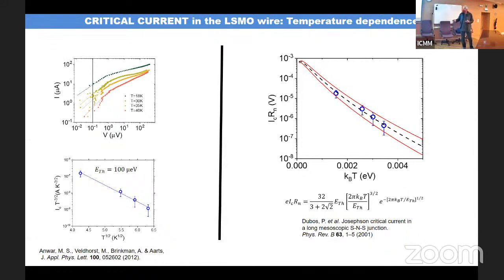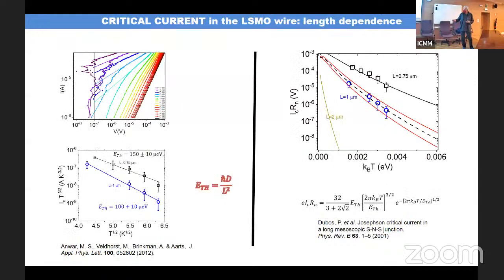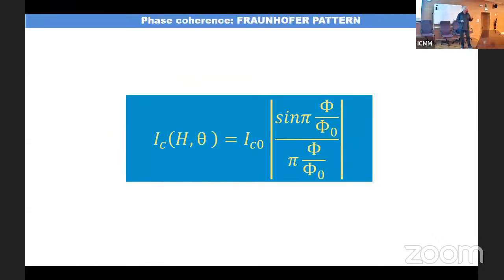And the values that we get for the characteristic energy, which is the Thouless energy, was also reasonable, 100 microelectron volts, which is comparable to what other people have found with ferromagnetic weak links. And we also obtained the correct scaling with the length. If we change the length of the weak link, the separation between YBCO electrodes, we get a scaling of the Thouless energy which goes as one over the separation squared, as expected. So this somehow makes a lot of sense. So we wanted to look at the phase coherence then.